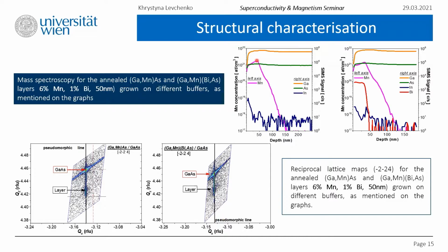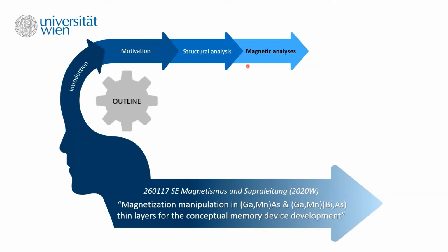Well, you see that the SIMS technique identifies the signal from all atoms, both those that are built into the lattice and those that are in the interlattice positions. Again, those interstitial defects. And the slightly lower signal from gallium and arsenic in the beginning corresponds to the surface oxidation distortions. Otherwise, we may say that, as proved by three techniques, we have high quality samples with a good zinc blende lattice, low concentration of defects, homogeneous throughout whole layers. With that, we can proceed to the measurements, which are the magnetic analysis.